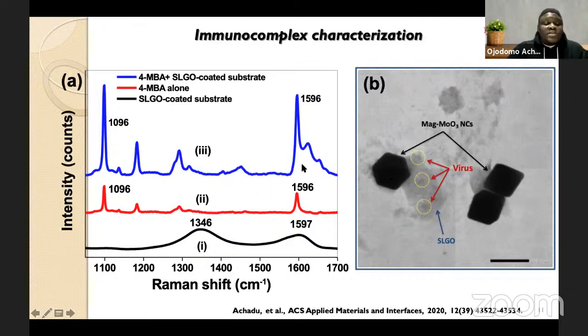So this spectra here is the Raman spectra that is generated. The black line shows us the graphene substrate alone without the reporter or the other SERS nanotag, and also in the presence of the nanocubes and also binding the reporter, which is the 4-MBA, we're able to see some bump and enhancement due to the graphene Raman signal and also the corresponding 4-MBA signal, which is shown in the red line. So with this Raman spectra, we're able to see that yes, we properly functionalized the surface of the graphene substrate with our reporter system.